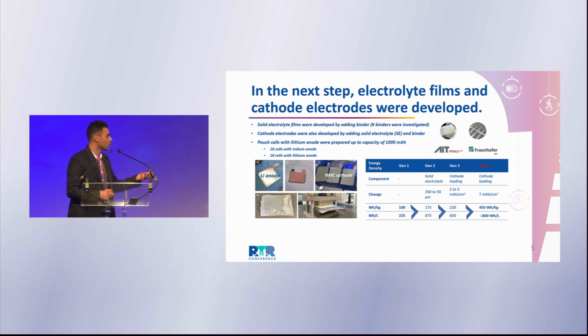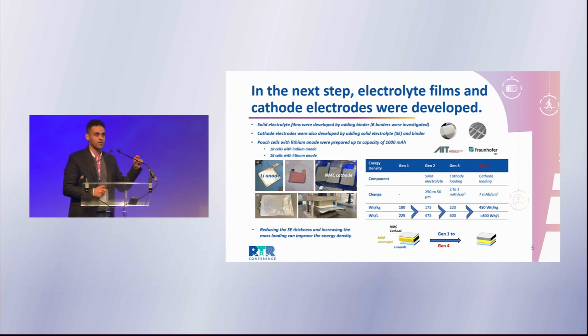So it was below our target, of course. However, in these cells, we were focusing on performance rather than just maximizing the energy density, because this was the first generation of the cells and we wanted them to really work. And so the solution to increase the energy density is that in the first generation, the thickness of the solid electrolyte is very high. It is around 250 micron. So we have to reduce the thickness to at least 15 micron, and we have to increase the cathode loading.